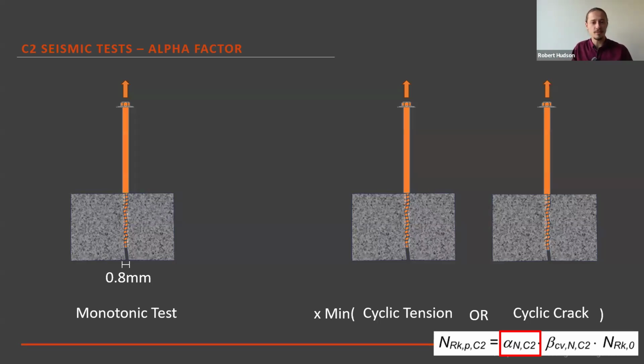And so we have a couple of tests we do. We have this monotonic test in the slightly larger crack width that's investigating what the additional crack width impact is. And then we do a cyclic tension test on the anchor in a crack, and we have the cyclic crack test. Now, one thing to highlight here is that we don't actually superimpose the impact of the cyclic tension test and cyclic crack test. This is quite good because otherwise the capacities would be even lower.